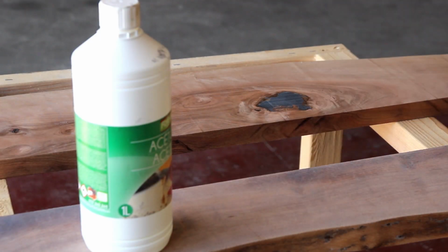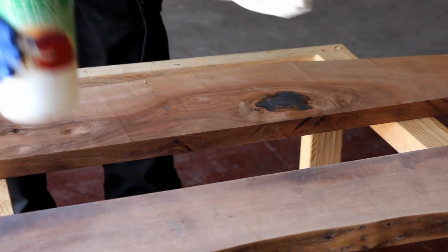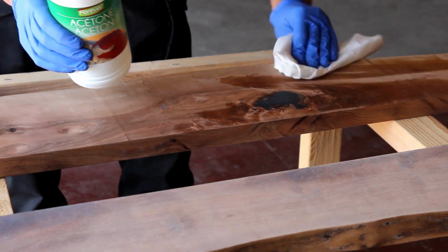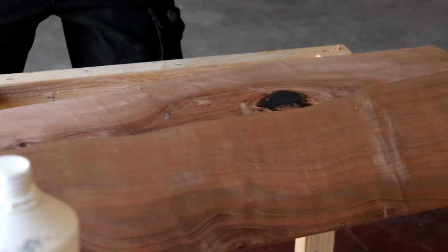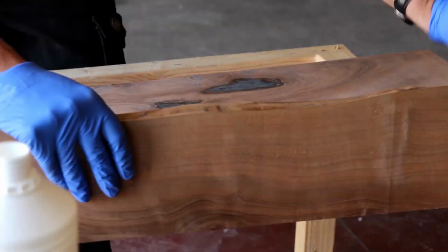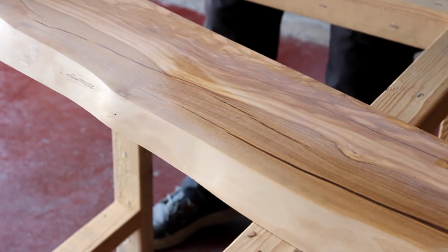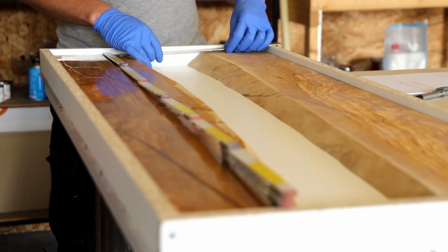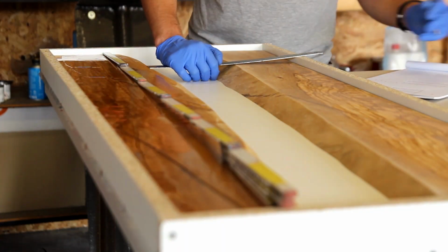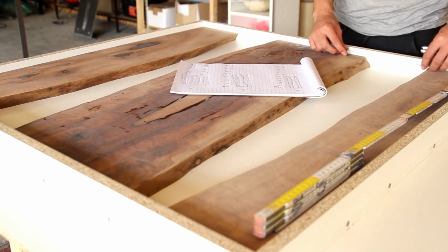The bark is not the strongest surface to bond the two surfaces together. I mean the epoxy resin and the bark, there's a big chance that it might break off, and mostly where it will happen is at the bark. So the bark will stay on your epoxy resin and the rest of the wood would fall off. That's why I'm removing all the bark, and then I'm just filling the voids with epoxy resin.